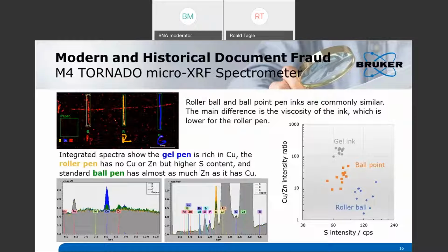So here, for example, once we know that we have three different typical materials, we can identify them. Let's say one seems to be characterized by more enrichment in zinc, where the other ones are more typical for a sulfur and copper enrichment. Once we cut the data, you see the green objects on top of each of these areas of interest, and at the bottom we see the cut spectra. So we can really detect that apparently more copper is related to a higher amount of copper photons in this area. A direct quantification is not possible, as we're not talking about a perfectly, infinitely thick or ideal sample, but we can create very nice element ratios and also get numerical classification, or possibilities to differentiate different types of material by element ratios.